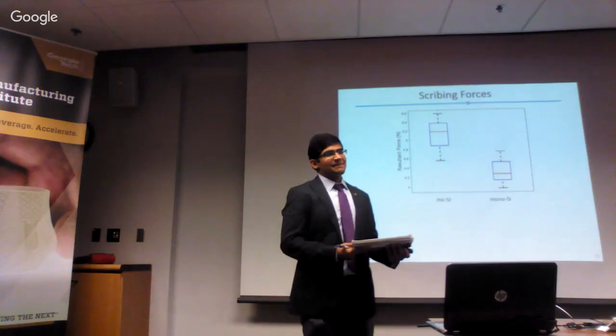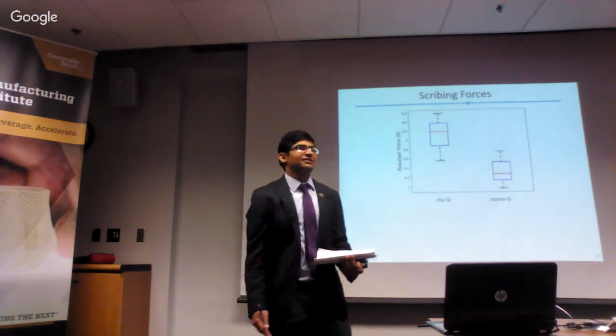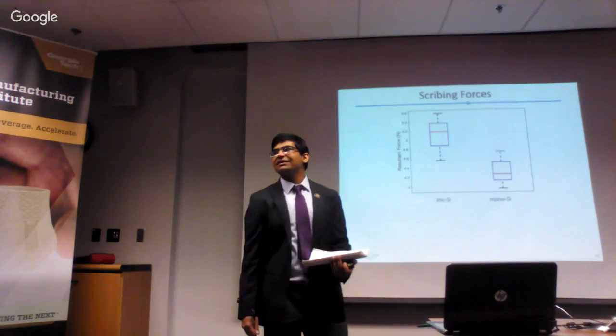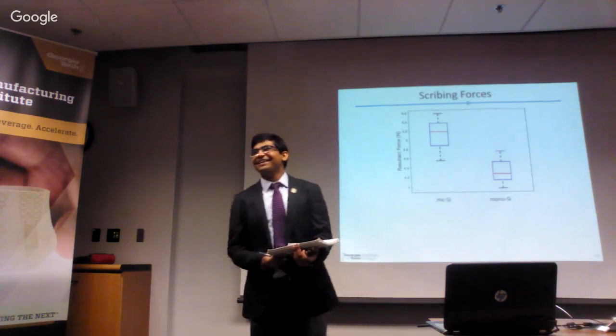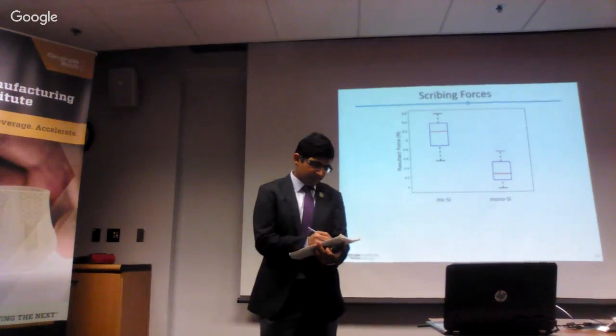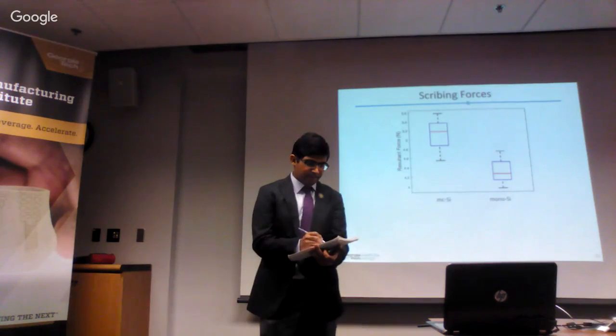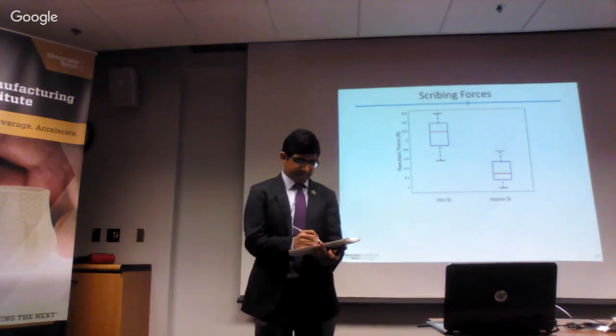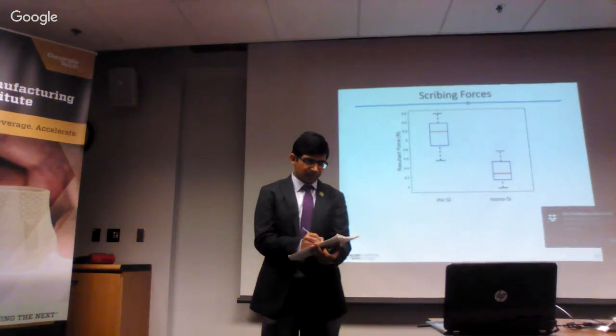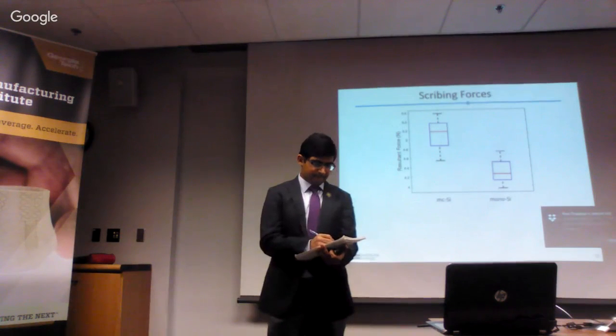That's interesting. I mean, if nobody's reported it, it seems like an interesting contribution. Well, we've done it. It was actually reported in previous work, but never received as much attention. Maybe we were excited about the fact that there is a correlation. Even in single crystal wafers, which have less crystal-growth-induced dislocation density, there are some, and there is a distribution. You can do dislocation etching, and in multi-crystalline silicon in particular, even within the grain interiors you have clusters with many more dislocations than others. In previous work by Arka and others, we looked at fracture toughness variations in those regions, as well as dislocation etching to identify them, and then used sister wafers for dislocation measurements. You see differences both in the scribing behavior and in the fracture toughness. Of course, that's an empirical correlation.